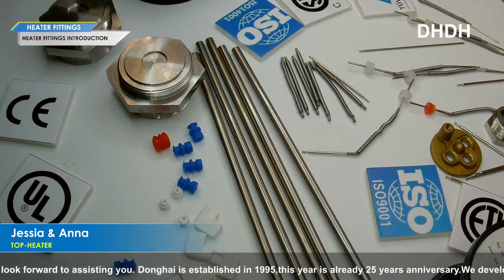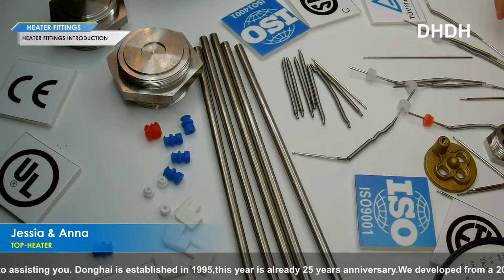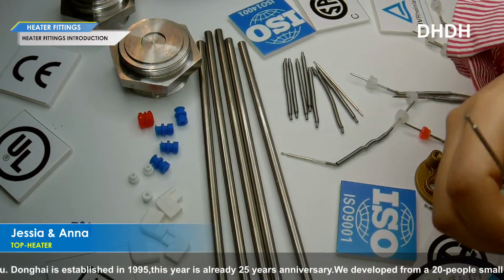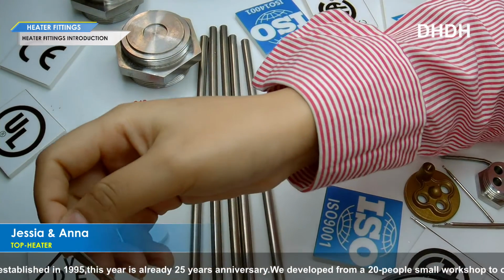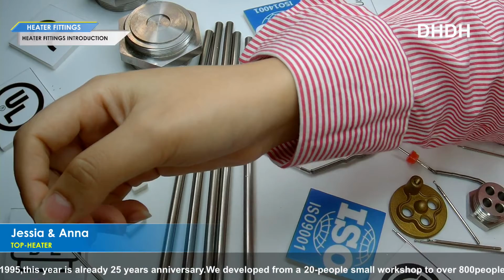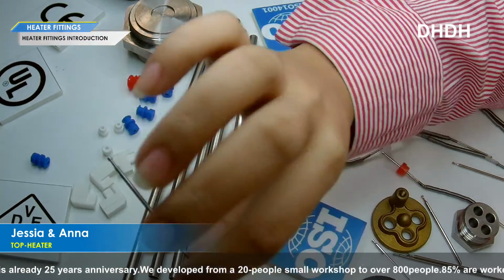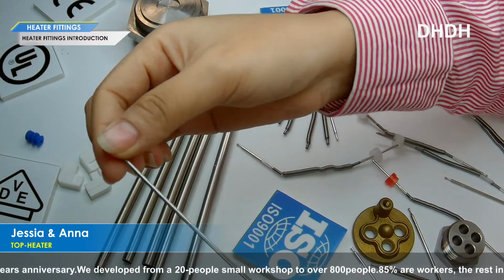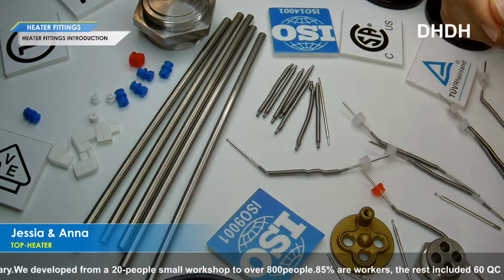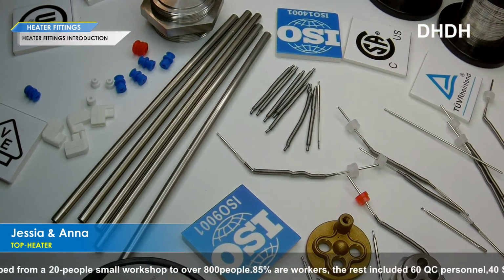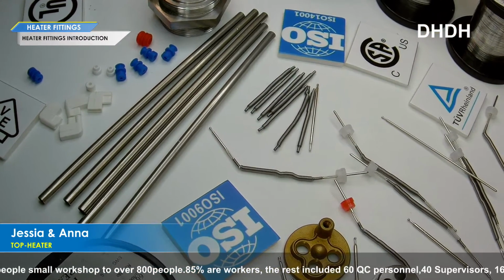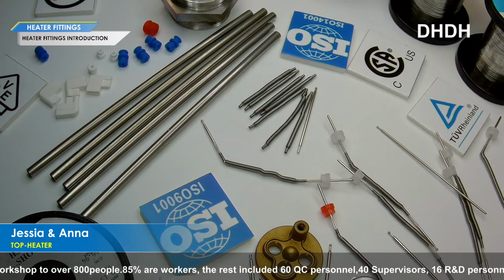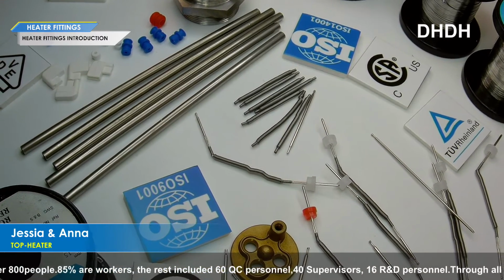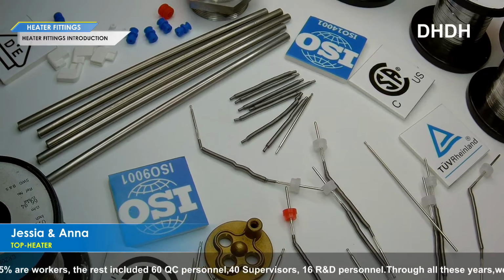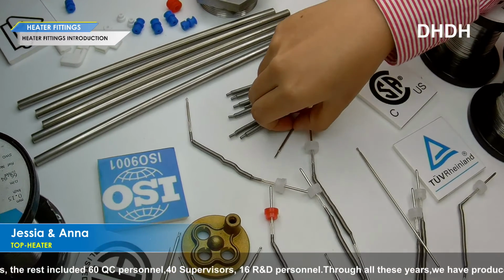Normally, our nickel coating thickness on the cold pin is from 1 to 4 micron. Yes, the nickel coating is to prevent corrosion. Normally, we suggest not to go over 4 micron, otherwise the welding with the pin might loosen. Yes, you can also see from our samples.